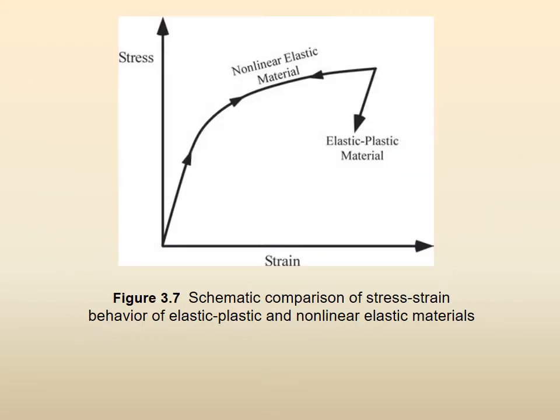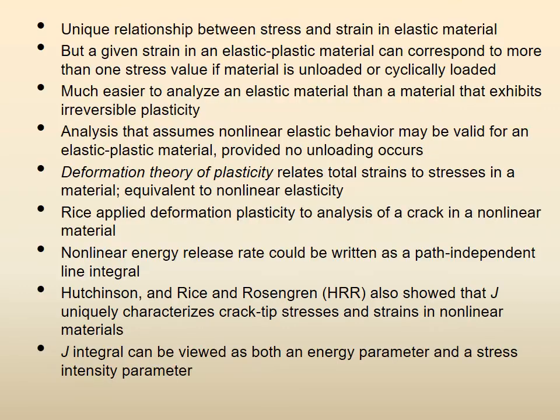We defined it and showed you the nonlinear elastic assumption of the material, where the loading curve is initially elastic and then curved plastic. But rather than unloading along the actual line, we assume that we unload on the same line. This becomes the theory of nonlinear elasticity, also called the deformation theory of plasticity.